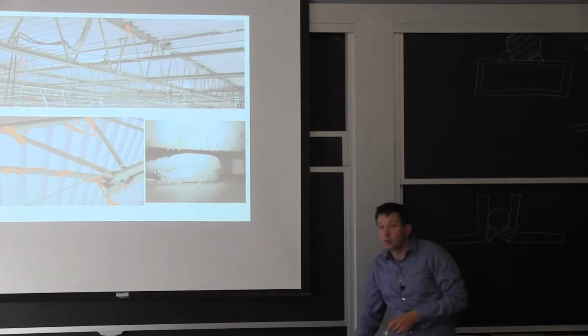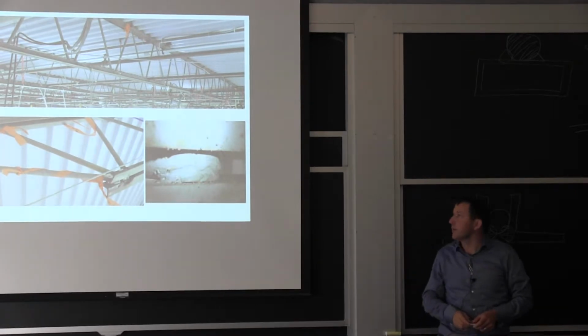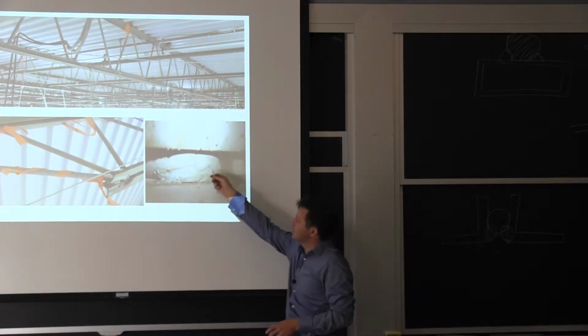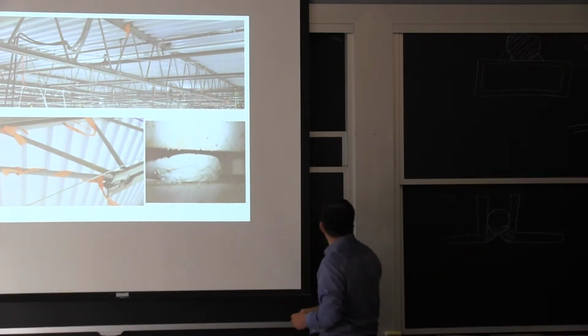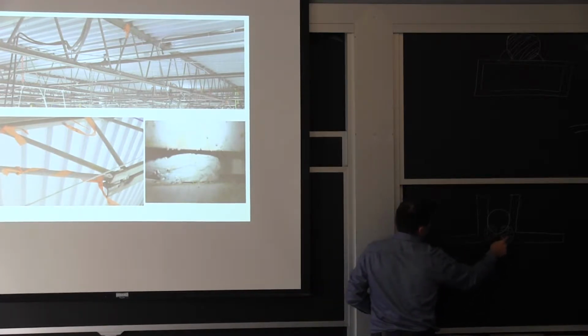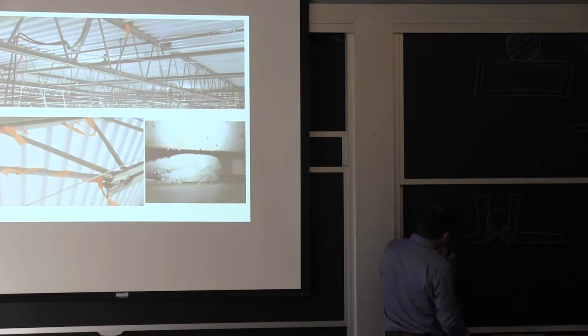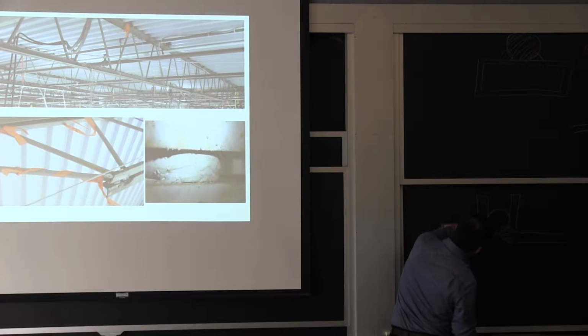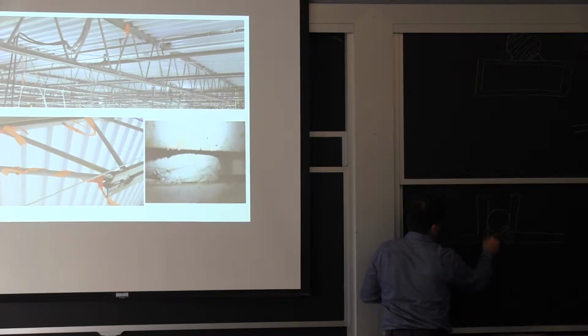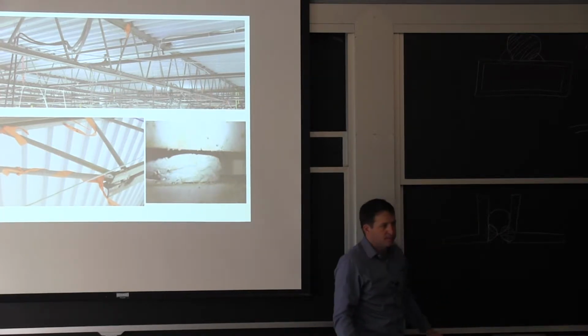So this one broke. There's nothing that really failed because it was still holding on the other side. But if you have two connections, you have two welds, you have one that broke, and the reason is it never fused. So it's essentially like this on one side, and it was just melted with this, but you just had a kind of a brazing interface on the other side.